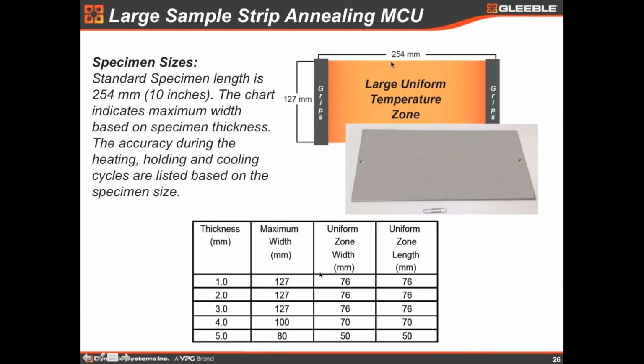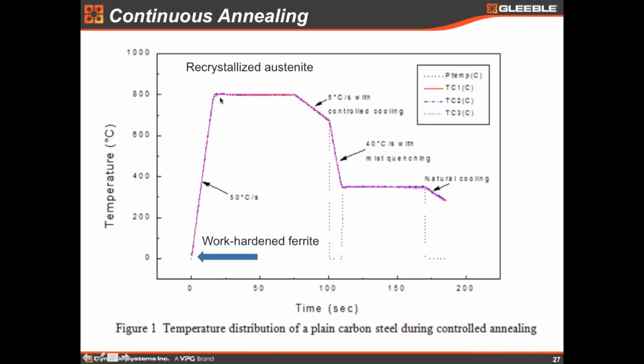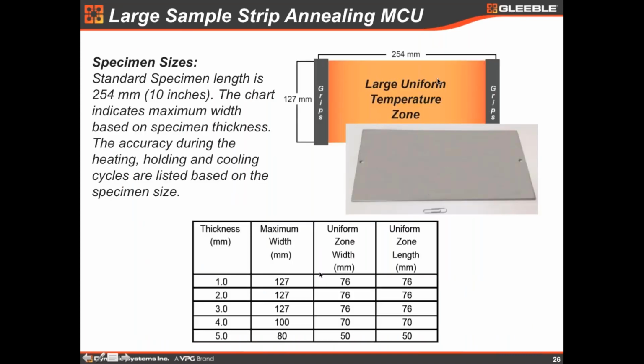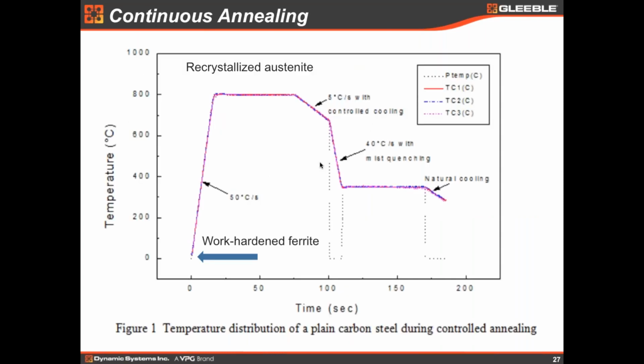test a sample. It's a quite big sample that we can test and run the exact thermal cycle that we have, that we plan, or that we want to improve in the continuous annealing line. But we have a very large uniform temperature zone in this specimen, so we can do, let's say, a hole expansion test. You can stamp a tensile sample in this big sample, and at the same time follow the exact heating cycle or thermal cycle that you have in the continuous annealing line.